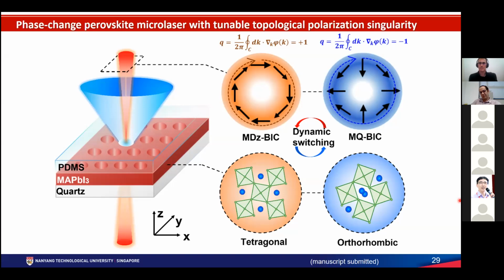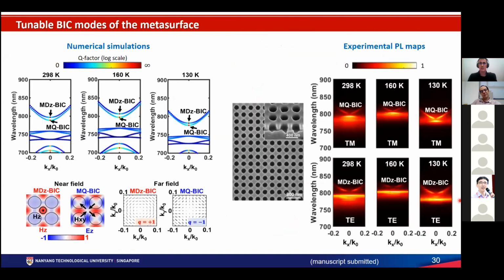Is the solution processed perovskite thin film quality good enough? Yes, it is very good actually. And you can see that when you do nano-imprint lithography, we observe that the quality of the perovskite becomes even better, because probably it is put under very high pressure and temperature during the nano-imprint lithography processing. Even the surface morphology becomes better, the environmental stability becomes better, and even lasing becomes better.